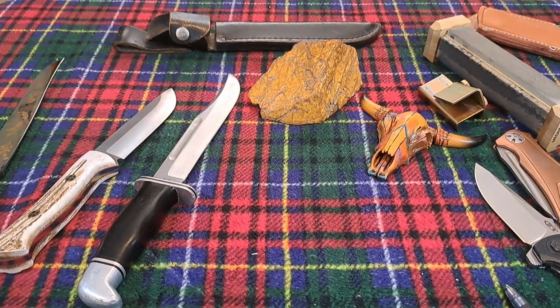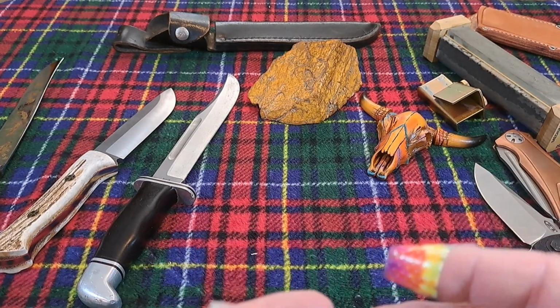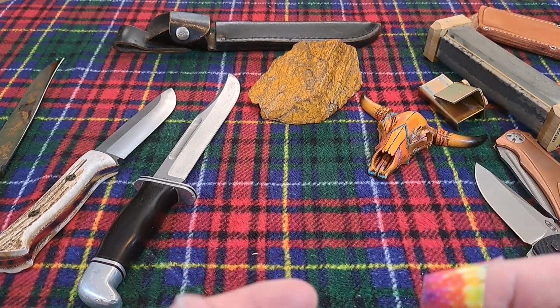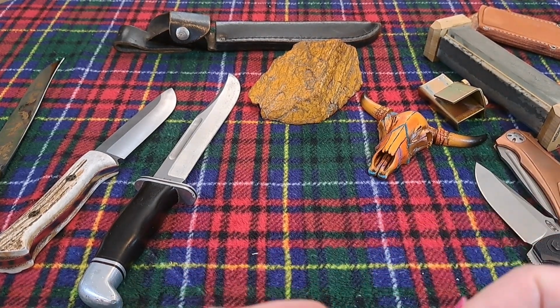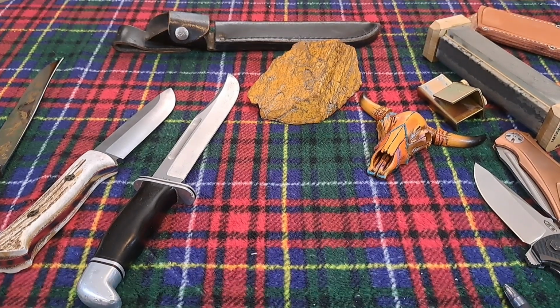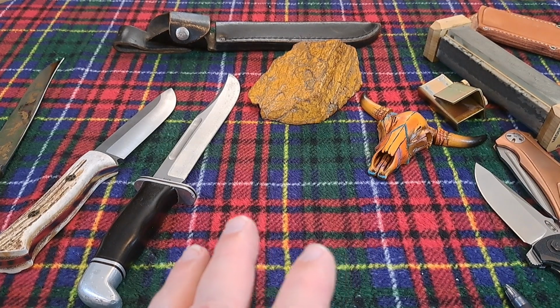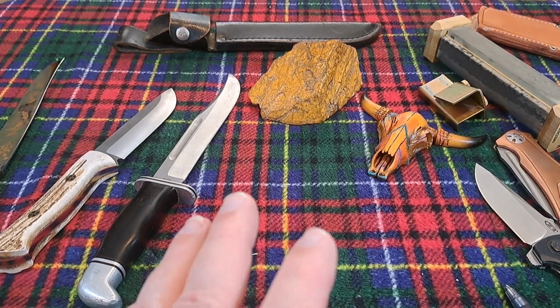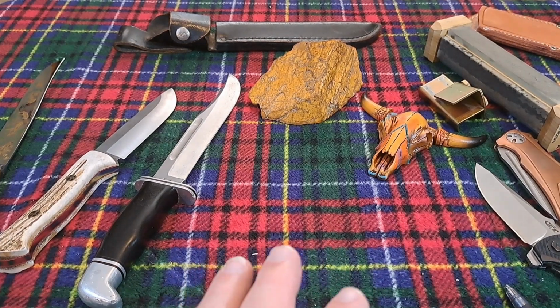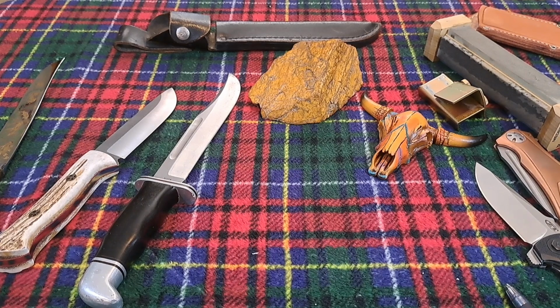And there are some steels, for instance stainless steels, that traditionally don't sharpen real well because they tend to mix with the carbon. They have a lot of chromium in them, and so you don't get superior sharpness out of that steel. But people have come up with creative heat treatments and temperings so that it works. A good example of that is the Boker heat treatment on 420HC steel. It's phenomenal, and it creates a great steel and a great sharp edge that you can repeat. And it's not a high-end steel. It's just an old normal steel, but it's how they heat treat it.